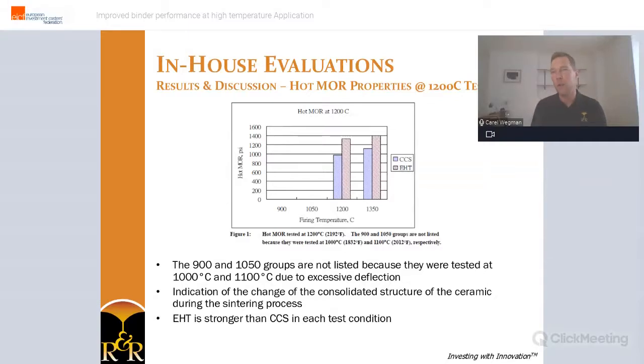The test results at 1200 degrees C need some further explanation. We expected to see the MOR increase as the initial firing temperature increases. But at the test temperature of 1200 degrees C, the test bars that were fired at a lower temperature of 900 and 1050 degrees C were too ductile to be broken. The samples bent to a point exceeding the allowable displacement of our testing units. These bars were eventually successfully tested at 1000 and 1100 degrees C, but we decided to leave this data out of the presentation because it was not in line with the objective and it could not be compared to the other data. And now you might wonder what is happening here at this low temperature.